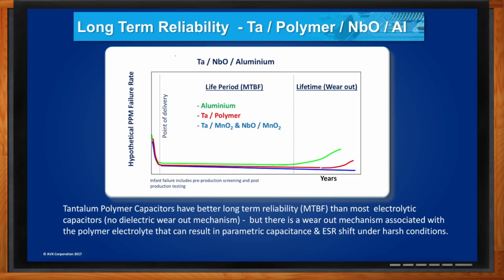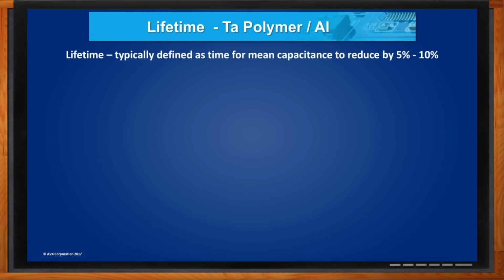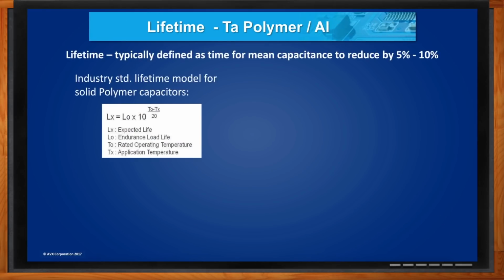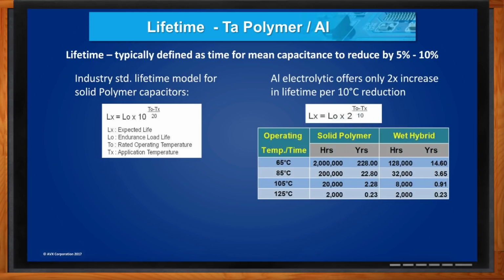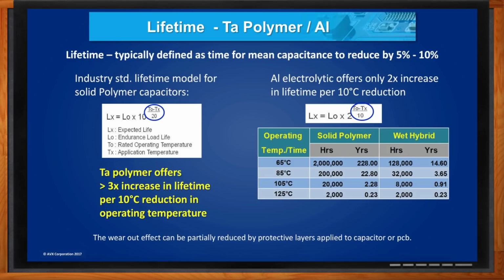Okay, Chris, so how does this compare with aluminum electrolytic? Now, for the polymer, that's interesting. Pushed to the extreme of voltage and temperature, it's similar to the wet hybrid aluminum. But the advantage with the polymer is as you drop the temperature, the lifetime actually increases faster than it does for the equivalent aluminum. So by the time you've got down to 65-degree operation, you're talking about hundreds of years compared to tens of years, with no significant capacitance change in the polymer compared to the aluminum.